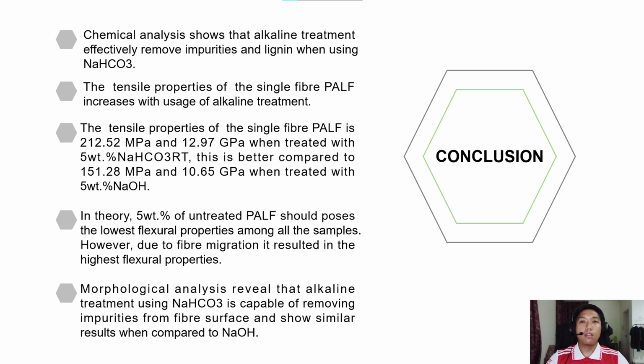For the composite, due to the experimental errors, we could not conclude our data accordingly, but we can see that the shift in the migration of the fibers could affect the results, and also the porosity or air bubbles could lead to different results compared to previous research. And finally, morphological analysis shows that the alkaline treatment using sodium bicarbonate is capable of removing impurities from the fiber surface, and it also shows similar results compared to sodium hydroxide or NaOH.